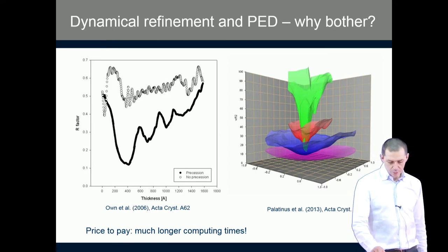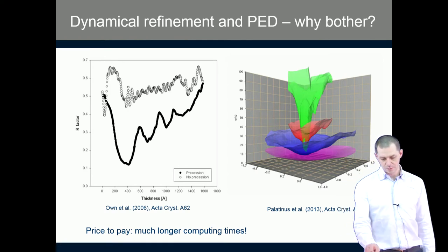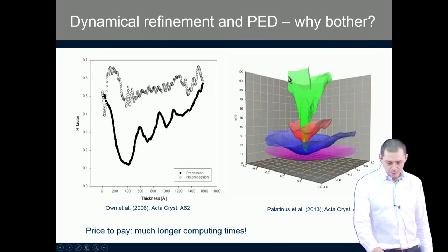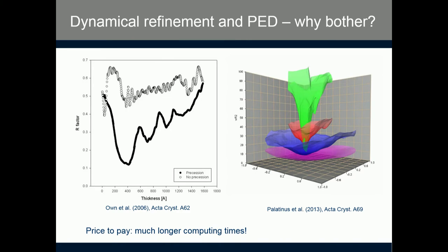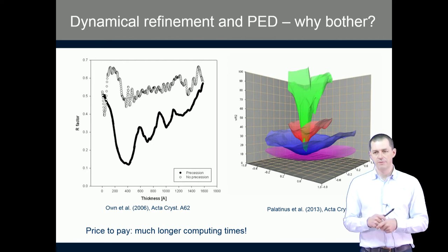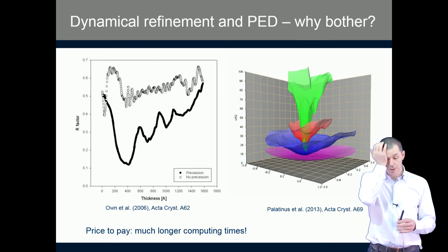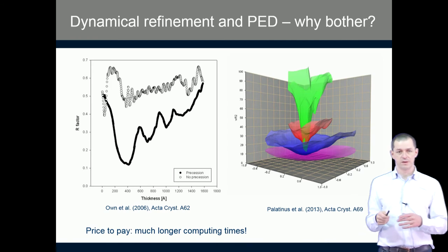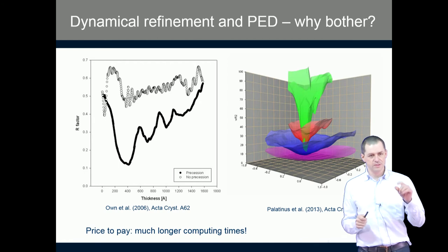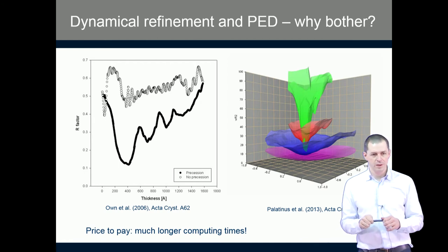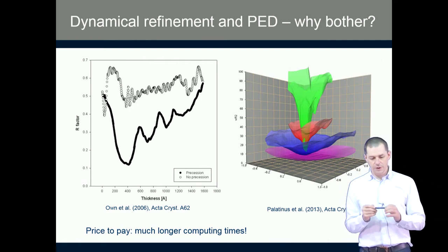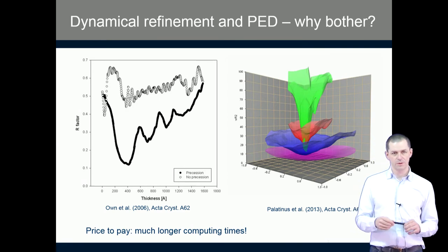This is another plot that shows the R value as a function of crystal orientation. This was done on a silicon crystal. So these curves or surfaces show how the R value changes if you tilt the crystal a little bit. And you see that the green curve, which is without precession, has a minimum, but it has a sharp rise of R values as soon as you move a tiny fraction of a degree. If you tilt the crystal by 0.05 degrees, which is an imperceptibly small rotation, the R value goes up from 5% to 40%. And it's this sensitivity to thickness variation and to the exact orientation that makes the fitting of diffraction patterns without precession extremely difficult, even with dynamical diffraction calculations.